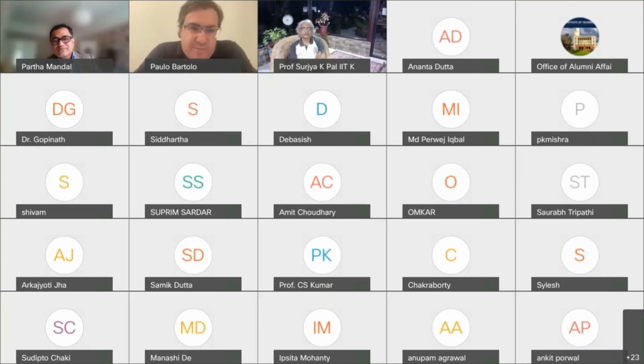We can incorporate these materials with polymers. But nevertheless, there are groups that are producing lattice structures made in titanium, and they are calling those structures scaffolds. I don't agree, but for me, a scaffold should be a temporary structure. And the role is to provide support for cells to grow and generate a new tissue, and by the end, the structure will disappear and we'll have a new tissue formed, which is not possible with a non-degradable metallic structure.